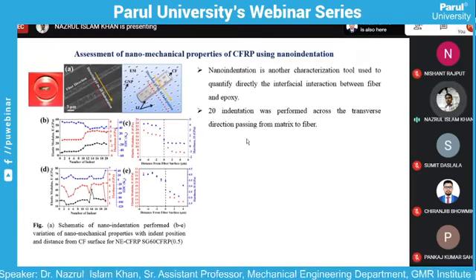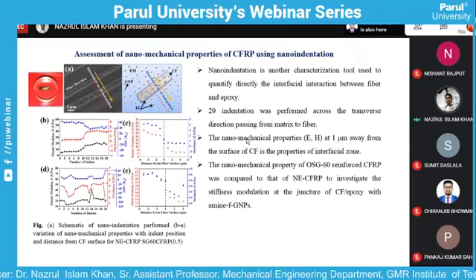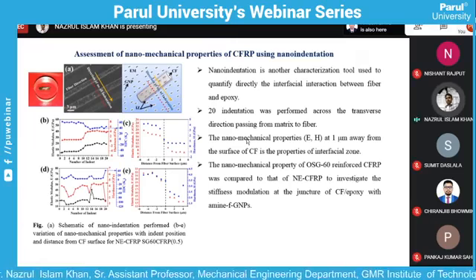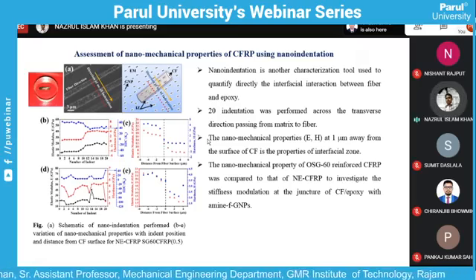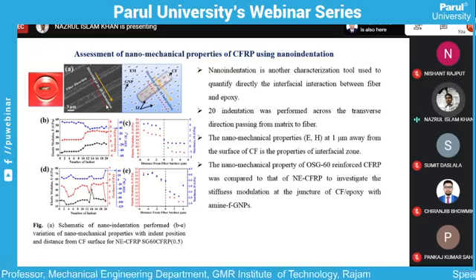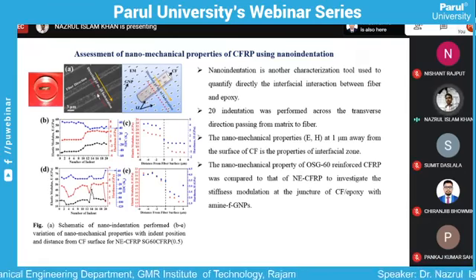We also found how to quantify the interfacial adhesion between the carbon fiber and the matrix material. For that we did nano indentation at IIT Kanpur, along the transverse direction of the carbon fiber and matrix, indenting on the matrix, approaching the carbon fiber, and then passing the carbon fiber.